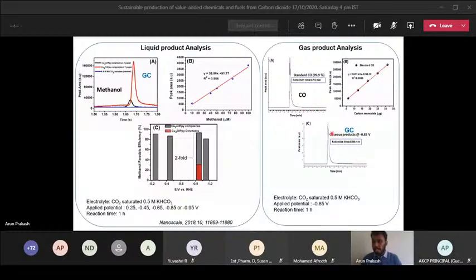This is for the standard carbon monoxide. We injected standard carbon monoxide and we got the signal, and at the same retention time we got the signal for our product, whatever gas we collected in the headspace of our system, and we confirmed that it is CO using the calibration plot. We did the electrolysis for 1 hour. We also did it for 15 hours, and we found it was really stable.